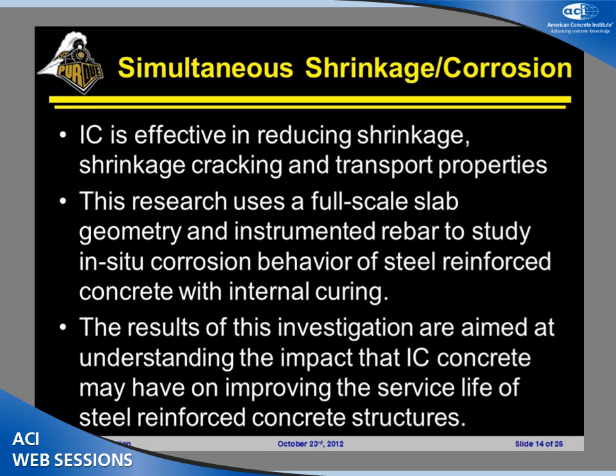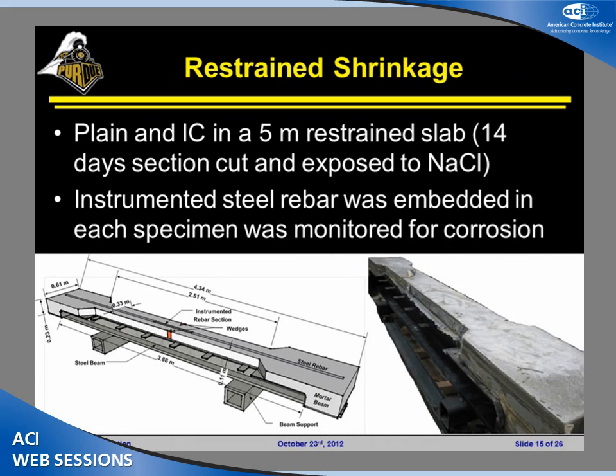And what we want to do is use a full-scale slab geometry that's instrumented with an instrumented rebar to start to look at how the corrosion is taking place in these 2 systems. All right, the results are aimed at really starting to understand a little bit better how internal curing is really going to alter service life, because neither one of these components on its own fully captures the behavior. So the idea here is we're going to place a plain and an internally cured system, and those are the 2 systems I'm going to be talking about today.